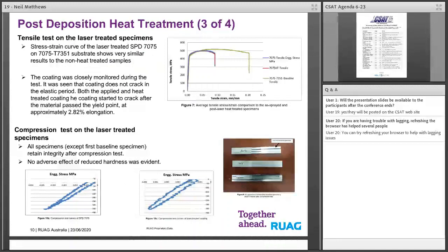So what we basically saw is we really didn't see any difference in the tensile behaviour or the compression behaviour. We did see some elements of increase in some of the yield strength, but our concern was our ability to control the tempering of the substrate. Very, very difficult with this concept of localised post-heat treat.